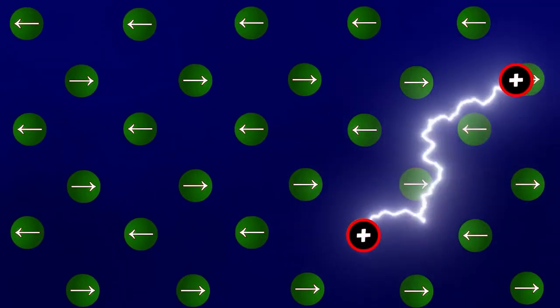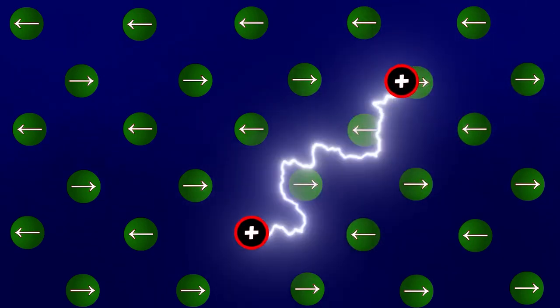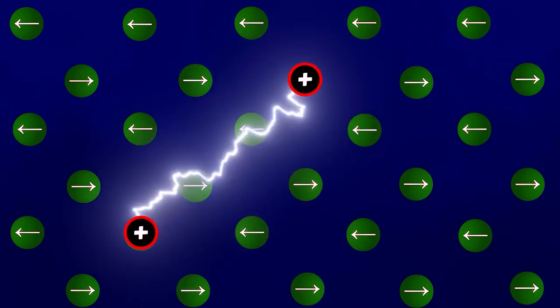Let's assume we have an acceptor mechanism, where external atoms snatch one of the lattice electrons. This creates a vacant spot, and the atom that lost the electron gains a positive charge. Thanks to this, under the influence of external forces like an electric field, an electron from another atom can jump into the vacant spot. The atom that was originally robbed becomes neutral again, but now a different atom gains a positive charge, and another electron from another atom can jump to it under the field's influence. This will appear as if a positively charged particle, a so-called hole, is traveling through the material. Now, let's examine the behavior of several such holes in our material, which, as a reminder, generally exhibits an antiferromagnetic orientation. These holes disrupt the antiferromagnetic structure, and it turns out that the energy of this disturbance is lower the closer the holes are to each other. In other words, the holes will start attracting each other, much like free electrons in a metal, but this time due to magnetic rather than electric forces. This magnetic attraction is one of the proposed mechanisms for the formation of Cooper pairs from holes in high-temperature superconductors, whose conducting layer possesses antiferromagnetic properties, like cuprates and other compounds.